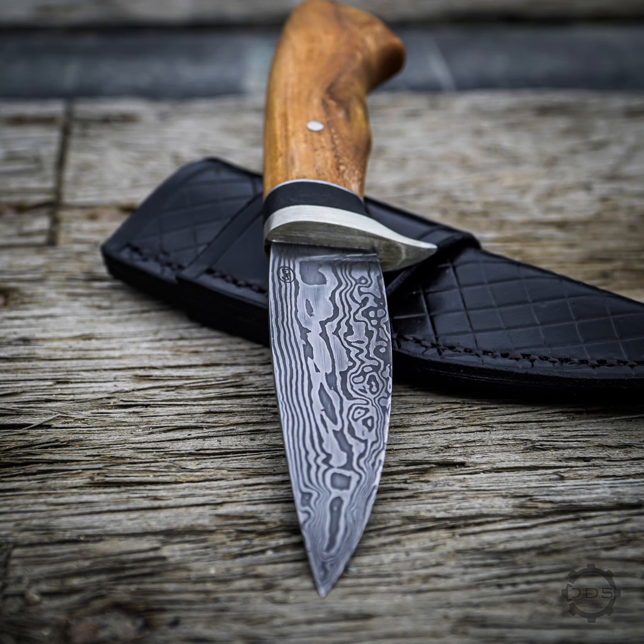So you have the case of a hidden tang that fails because the heat treat was not correct and the construction was wrong. And so it kind of gives hidden tang knives a bad rap. But if the blade is constructed properly, and you've got radius shoulders, and you've got a tang that, generally speaking, has the heat treat of a 16 penny nail, it's soft to springy. It's not going to break, and you can use and abuse it in a big way. And this is not going to be the part of the blade that fails. So it's encased in epoxy.